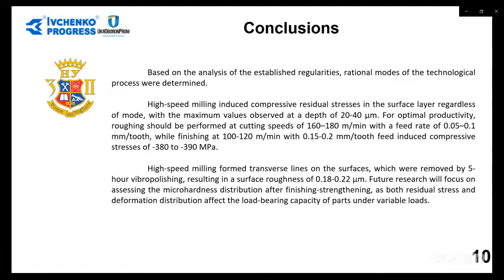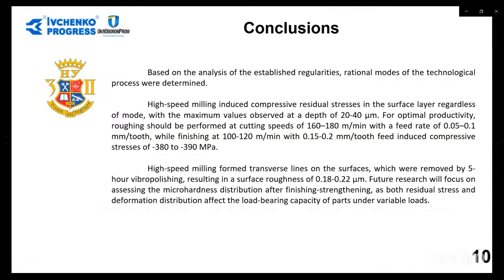High-speed milling induced compressive residual stresses in the surface layer regardless of mode, with the maximum values observed at a depth of 20 to 40 micrometers. For optimal productivity, roughing should be performed at cutting speeds of 160 to 180 meters per minute, with a feed rate of 0.05 to 0.1 millimeter per tooth, while finishing at 100 to 120 meters per minute with 0.15 to 0.2 millimeter per tooth feed induced compressive stresses of 380 to 390 megapascals. High-speed milling formed transverse lines on the surfaces, which were removed by 5-hour vibro polishing, resulting in a surface roughness of 0.18 to 0.22 micrometers.